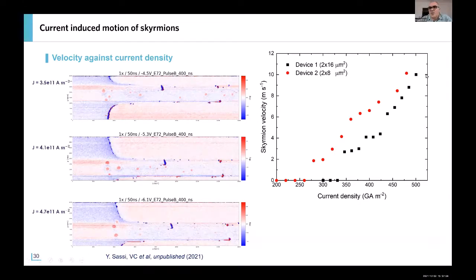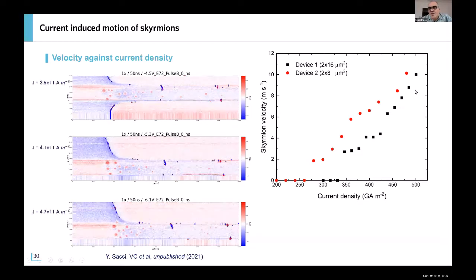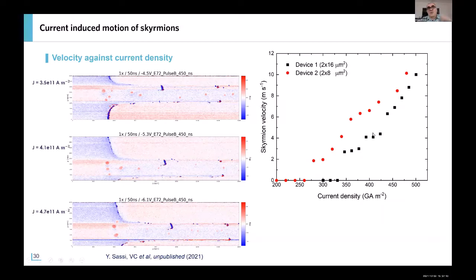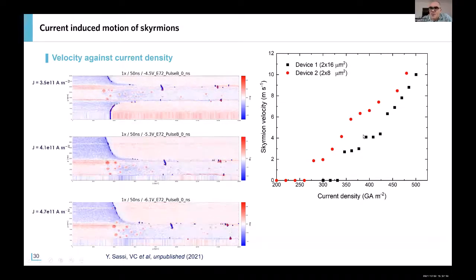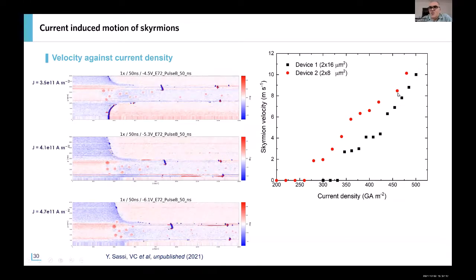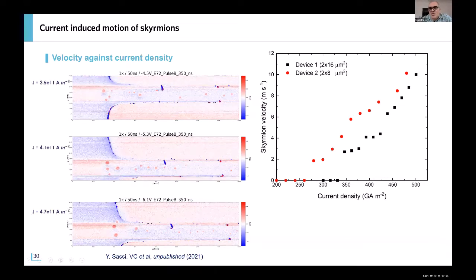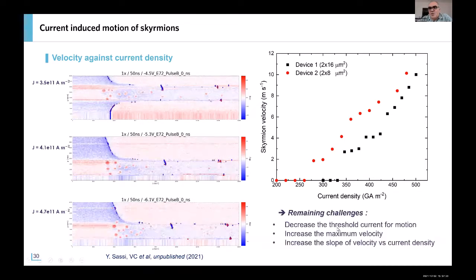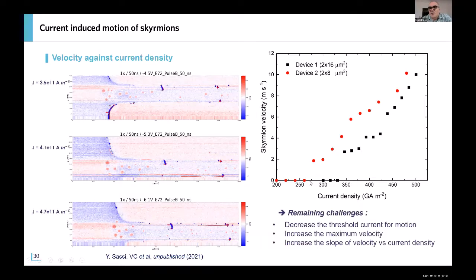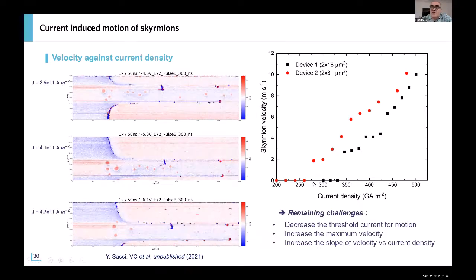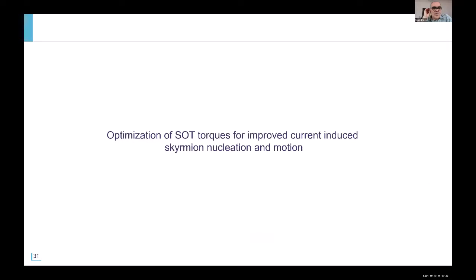We have velocities of about 10 meters per second, but these are really the average of a large number of events. This shows that we can increase the velocity, and the purpose will be to further increase the maximum velocity by increasing the current, but also to decrease this threshold. That is also an issue today for the motion experiments, and to increase the slope here of the velocity versus current density.